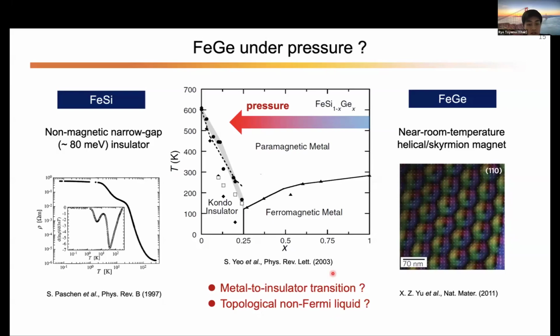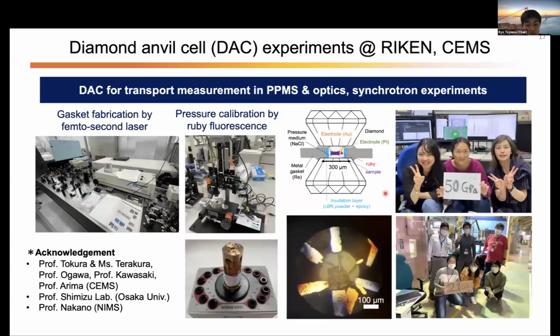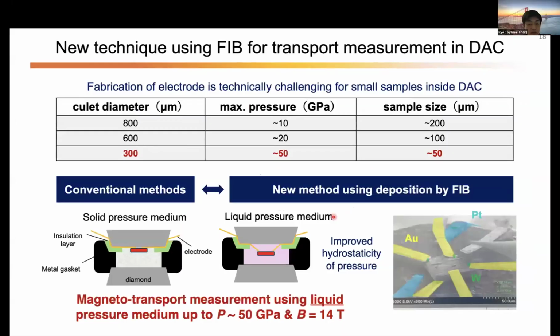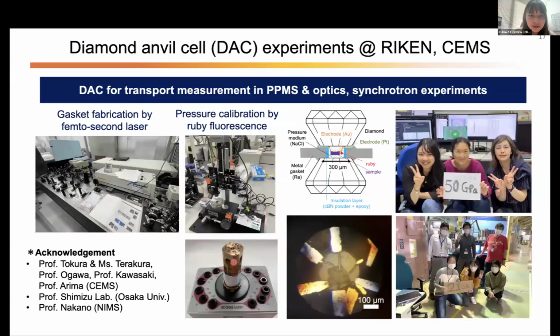You developed the new system to measure transport in an extreme condition. Is it possible to measure the transport with some annealing or high temperature along with the high pressure? So you mean high temperature, like how many? Maybe above the room temperature. So we are using a machine called PPMS for transport measurement, and in that case, we can reach 400 Kelvin at maximum. But in general, there's no limit for the upper temperature for this diamond anvil cell. So we can increase further if we use different apparatus.